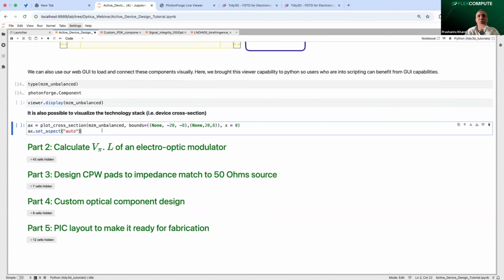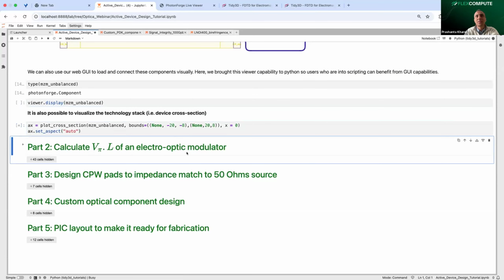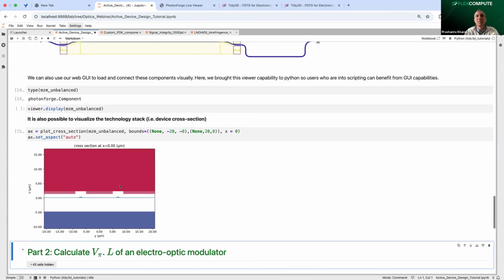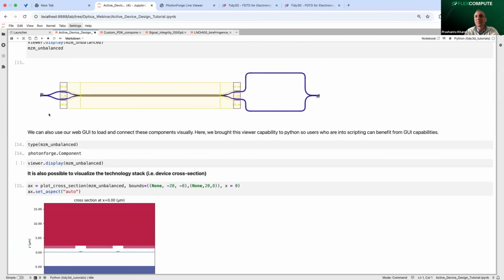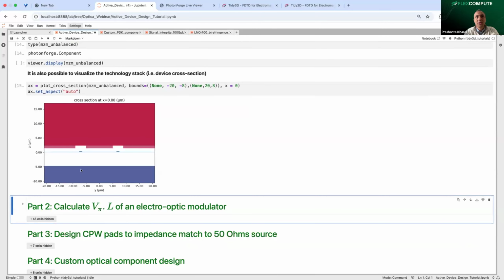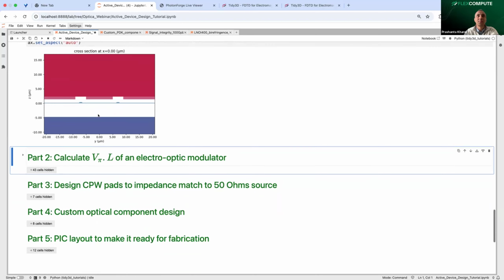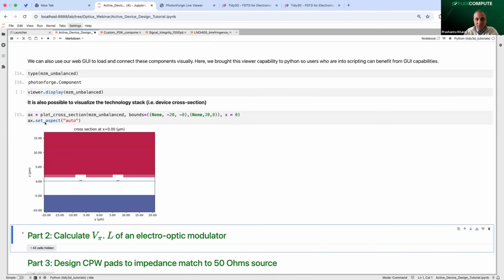But it's also possible to visualize the cross section of this device. In this case, I'm going to plot the cross section at x equals 0 for this unbalanced Mach-Zehnder interferometer. You can see the silicon substrate, the 4.7 micron thick box, and a very thin layer of thin film lithium niobate with waveguides defined in it. Then you see the transmission line, so ground, signal, ground, and above the transmission line, you have air cladding. I'll pause here and see if there are any questions.